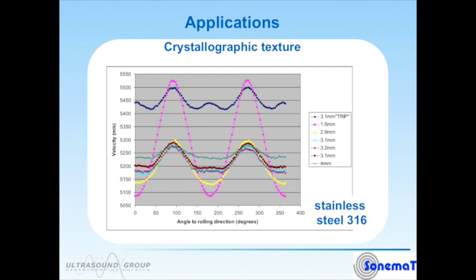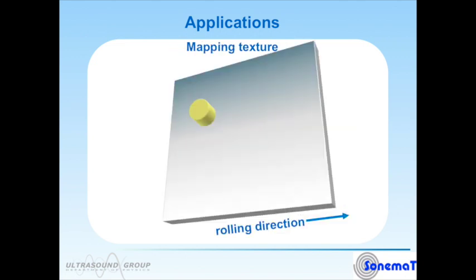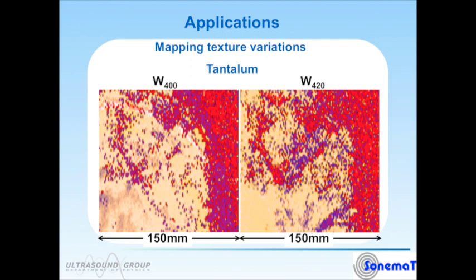This is useful information. It can tell you whether the processing has led to the right elastic and subsequently plastic properties. So previously we talked about mapping stress. We can also map texture. In this example we just use a shear wave transducer, and again we're measuring the acoustic birefringence. We're not building up a complete picture of the crystallographic texture, but we are building up part of that picture.